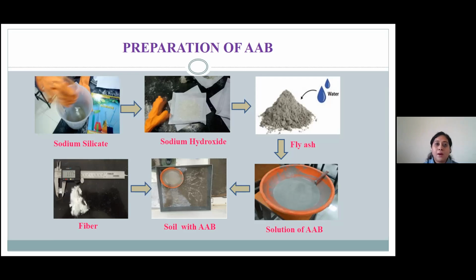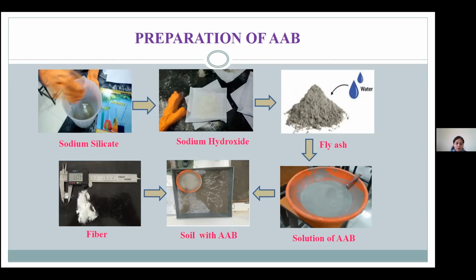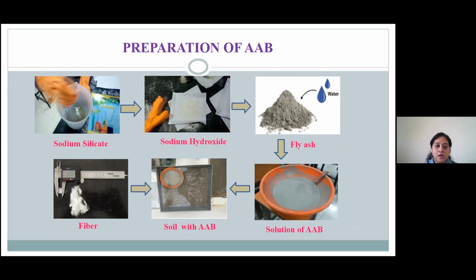This optimum binder content in the soil is chosen based on its workability, the alkaline reactivity, the binding efficiency, with low emission of greenhouse gases. Then, after mixing of AAB, we have covered it with jute bags for the next 3 days, around 72 hours, at room temperature, so that the excess heat which is arising due to the geopolymerization reaction evolves out.